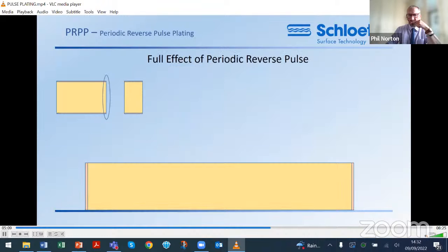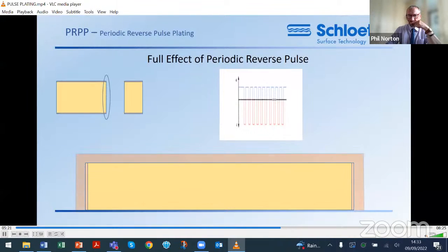The periodic reverse pulse plating cycle typically comprises a continuous cycle of normal DC plating with regular periods of reversal. This gives the overall effect of evening out the plating thickness, as is represented here.